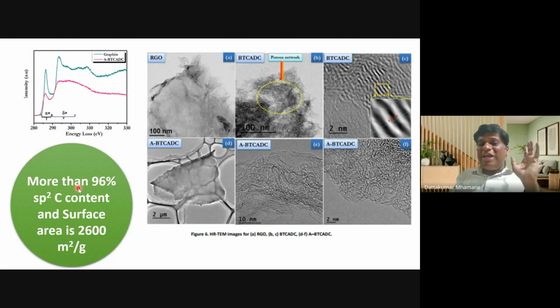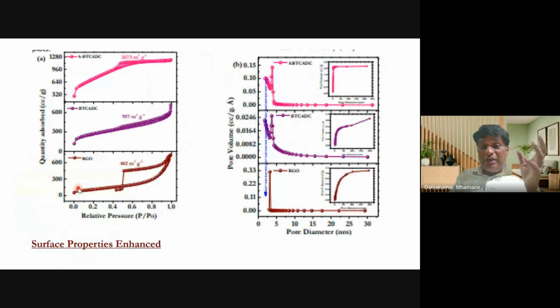So both the challenges we achieved in our carbon related work. You can see this is the carbon without activation. It is also 1000 meter square per gram. So this is a bottom up approach. I mean, from small benzene molecules we got a graphene sheet like this, okay, with a specific surface area of around 1000 meter square per gram. But in case of hydrogen reduced graphene, it is not even 500 or say 600. So we almost doubled the specific surface area, and we activated this sample, and we got around 2675 meter square per gram of surface area.